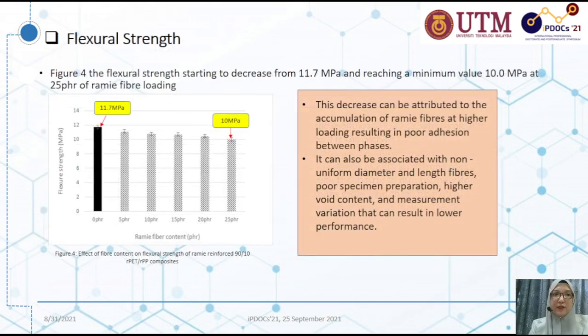Next is flexure strength. From figure 4 here, the flexure strength starts to decrease from 11.7 megapascal, reaching a minimum value of 10 megapascal at 25 pHr of Rami fiber loading. This decrease can be attributed to the accumulation of Rami fibers at higher loading, resulting in poor adhesion. It can also be associated with non-uniform diameter and length of fibers, poor specimen preparation, higher void content, and measurement variation that can result in lower performance.